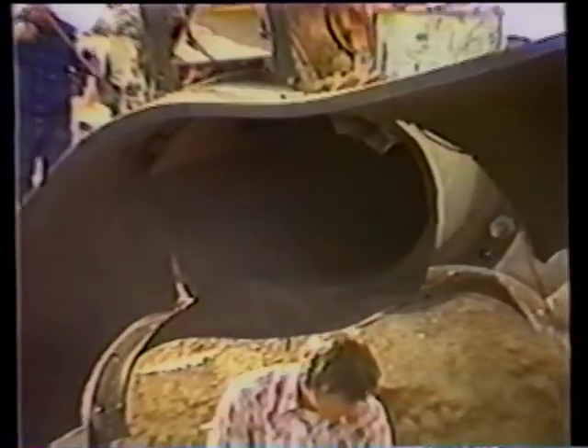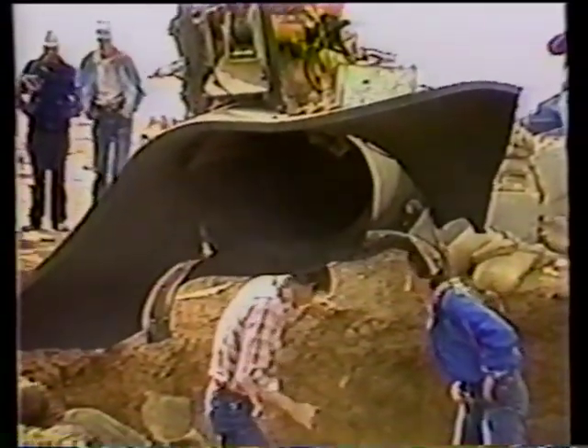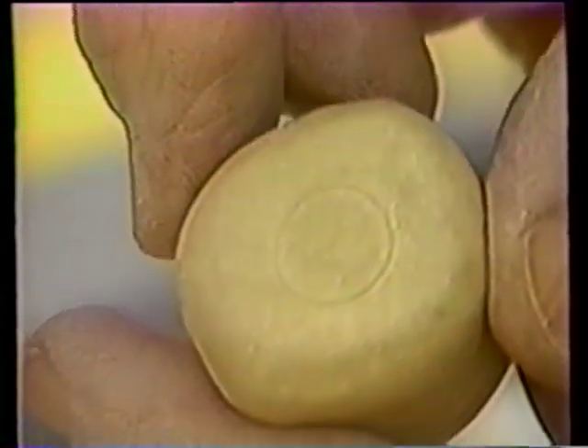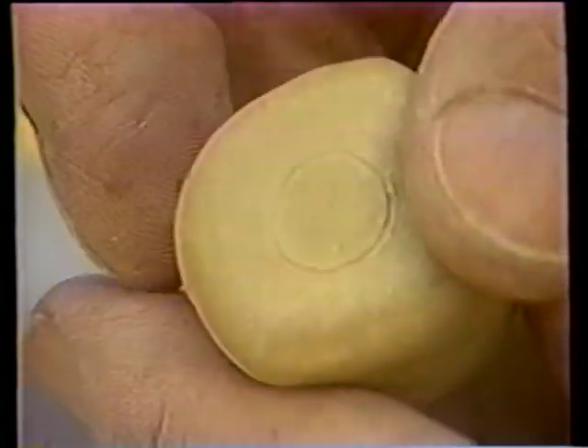12 explosion tests simulated the blast overpressure that might occur in an explosion of the launch vehicle. These tests spanned the pressure range from 200 pounds per square inch to 2,200 pounds per square inch, beyond the range expected in a Titan Centaur explosion. None of the fuel capsules was breached by overpressure.